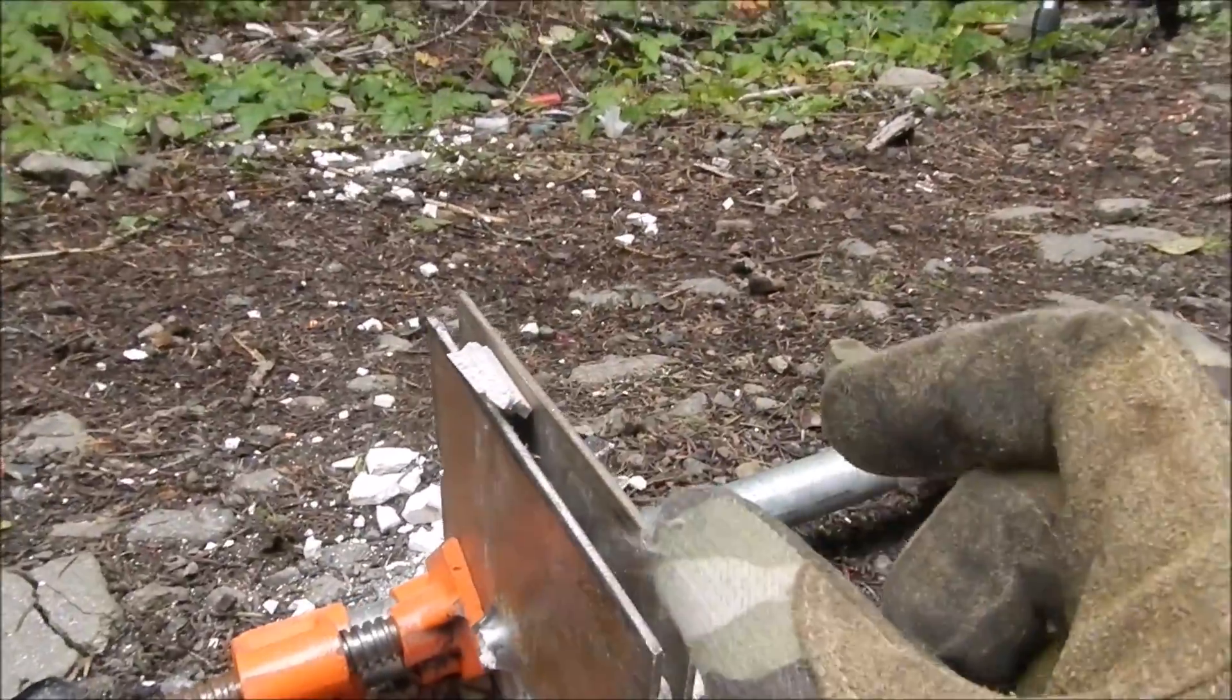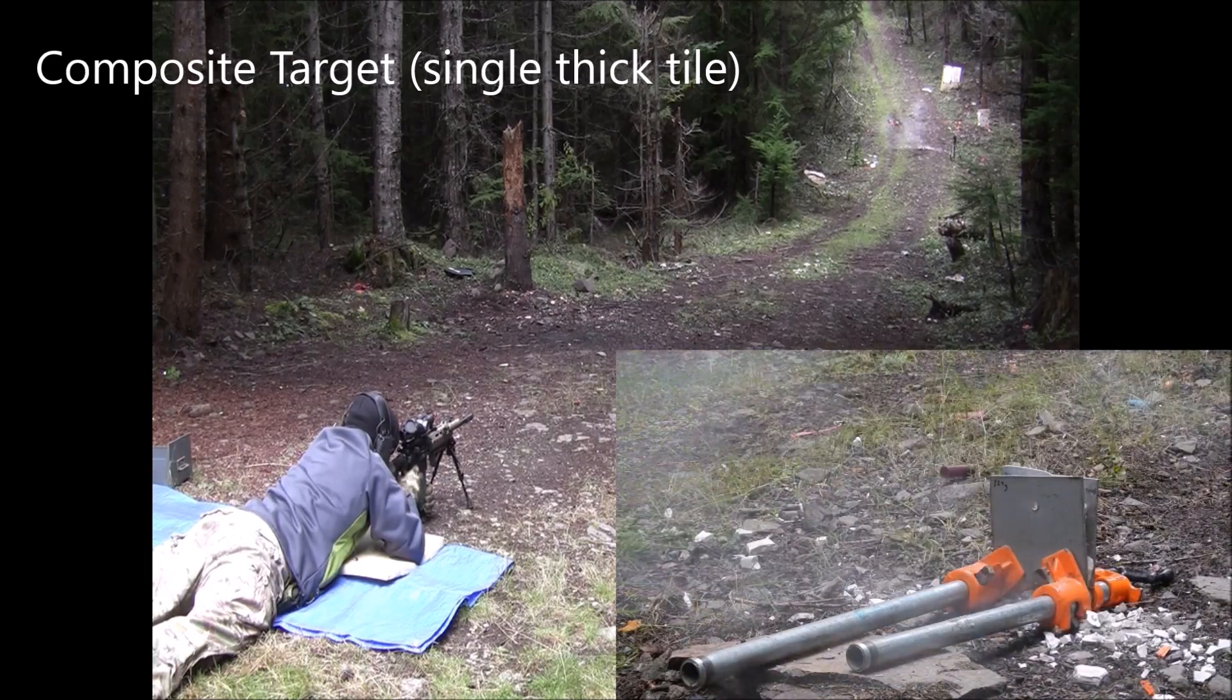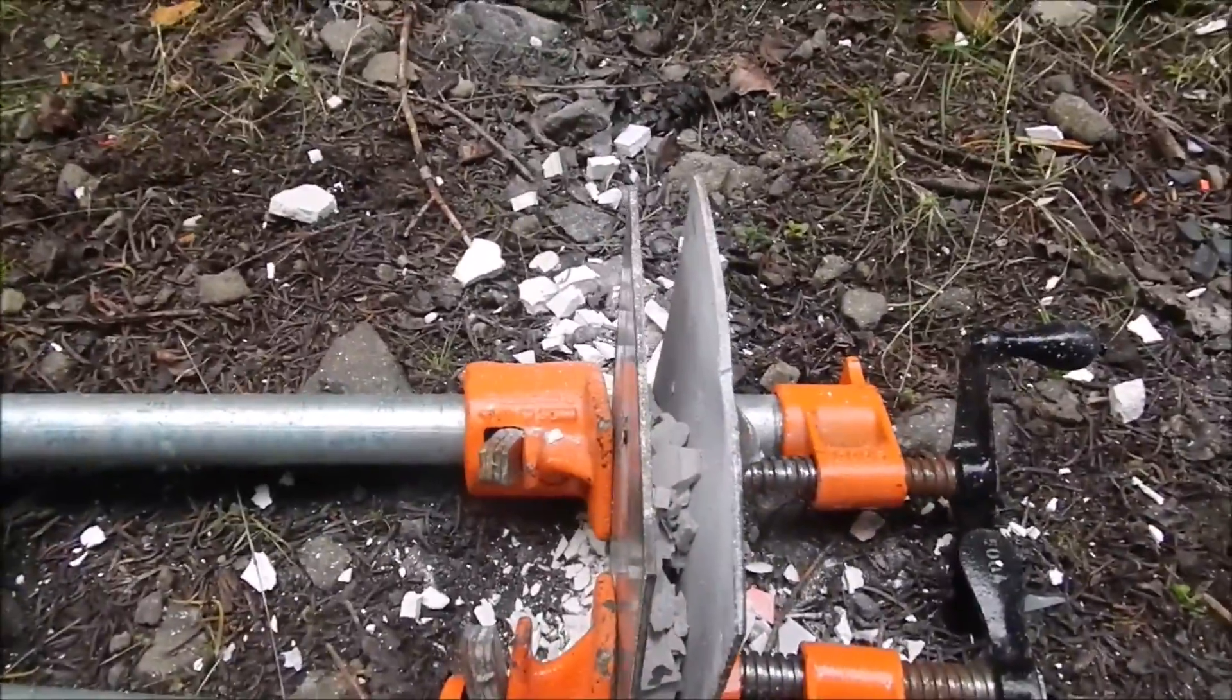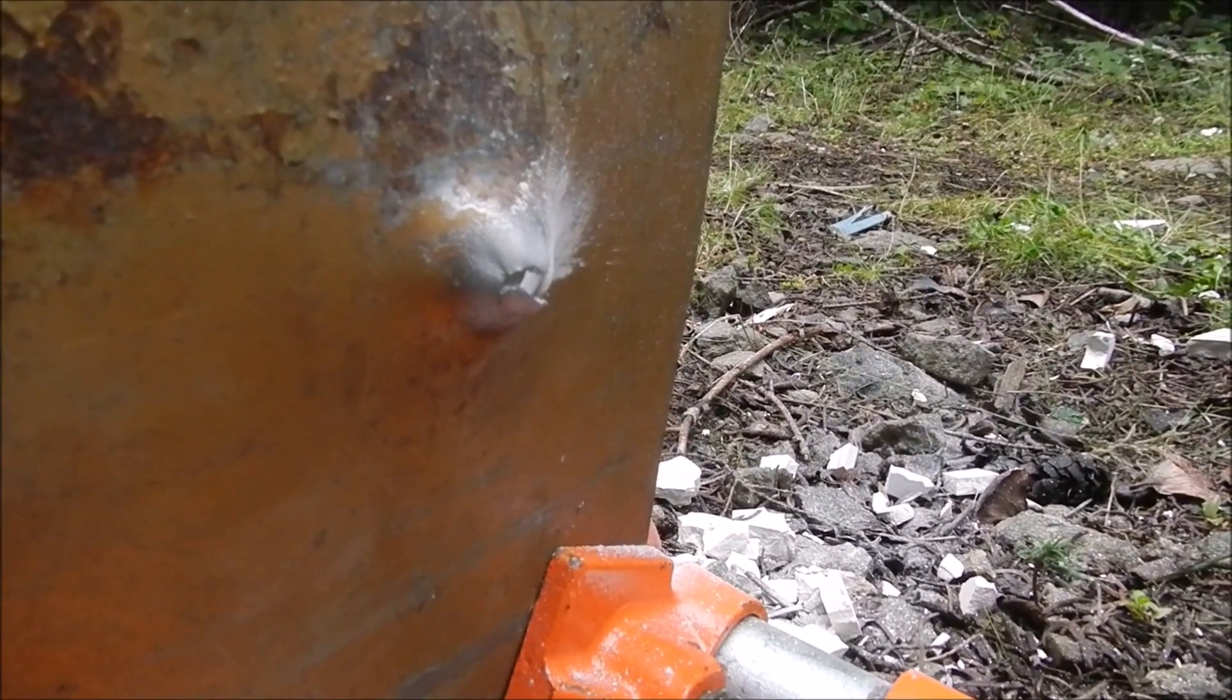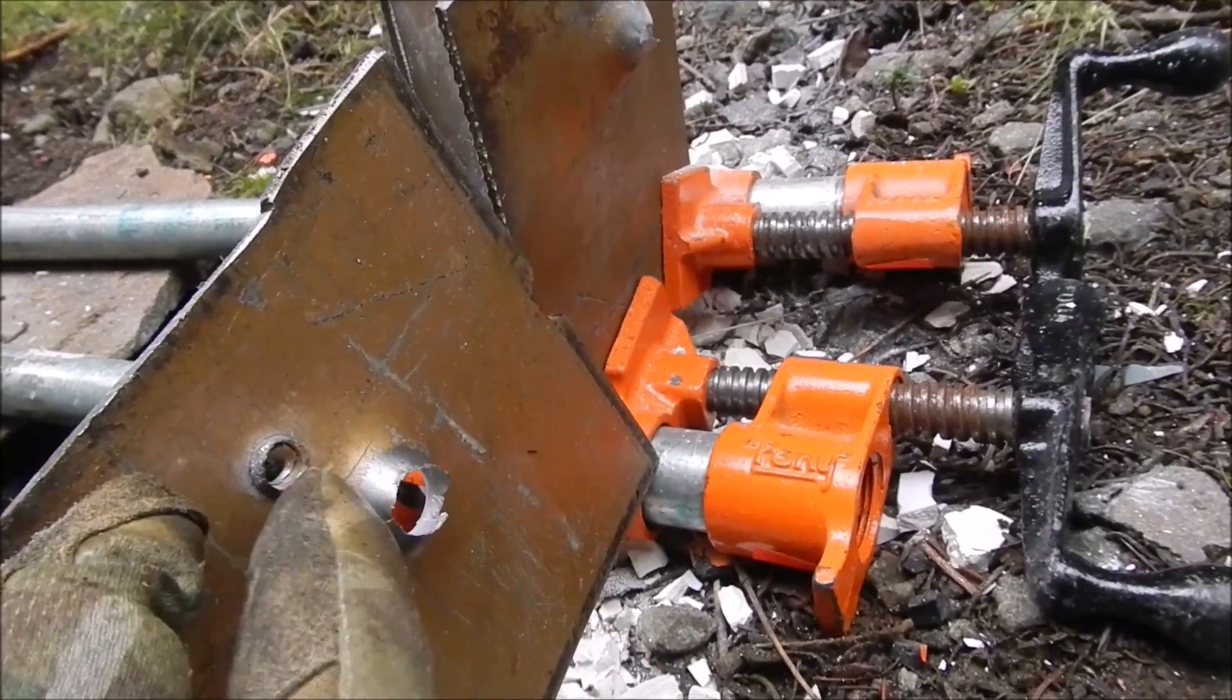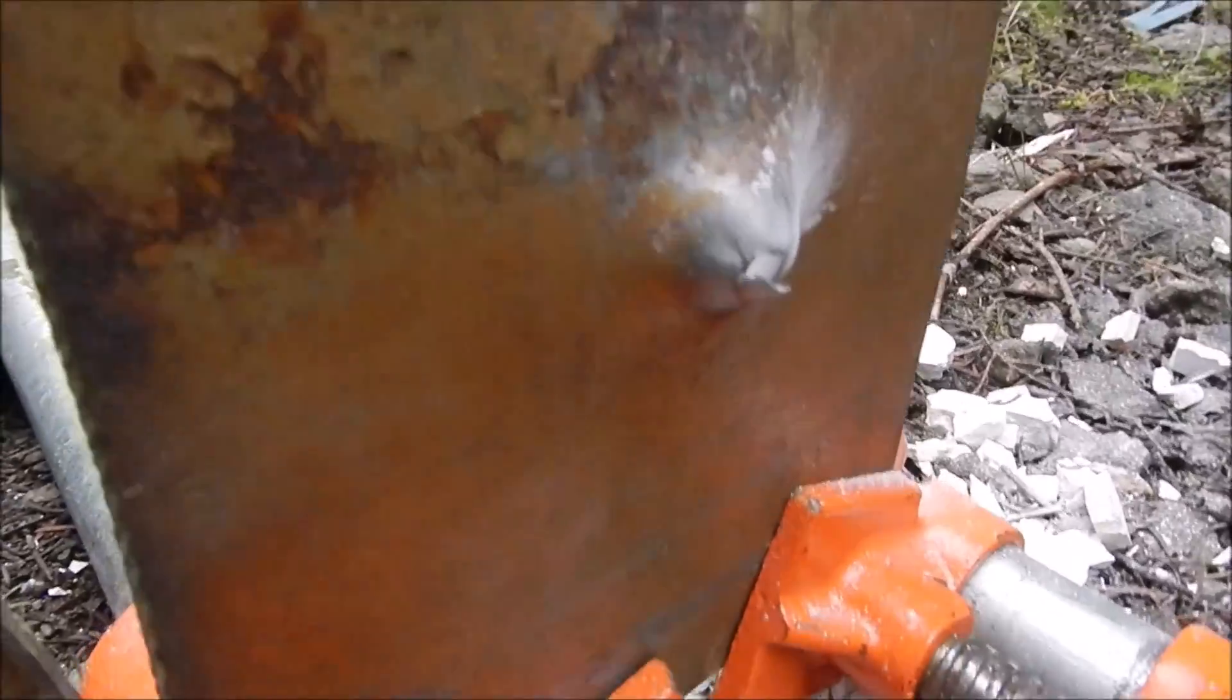Let's move on to where we use a much thicker tile in place of that thin one. We have a small entry hole through the front plate. The tile is of course totally obliterated. There is a large bulge and a small exit hole on the rear of the back plate. Let's compare this with using the thin piece of ceramic. We had this large exit hole using a thin piece of ceramic, but when we scaled up the ceramic in the middle, the exit hole was much smaller.